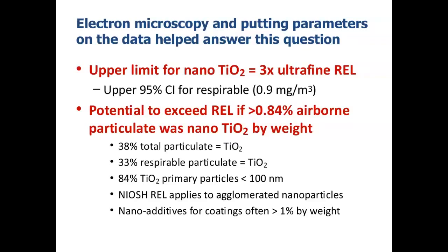So although the nanoscale fraction of TiO2 by weight was undetermined, we knew that 38% of the total particulate was TiO2, 33% was respirable by weight, and in addition, it's important to point out that the NIOSH REL does apply to agglomerated nanoparticles, and we can revisit the findings I showed earlier with the lab estimating that 84% of the TiO2 primary particles in the paint were nanoscale. Last but not least, one of the anonymous peer reviewers of our paper astutely pointed out that nanosized additives for coatings are typically added in the range of approximately 1 to 5% by weight.